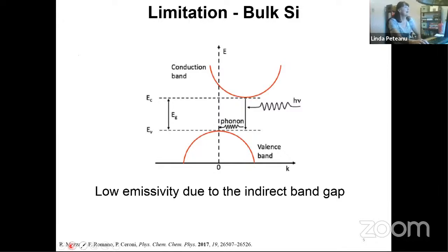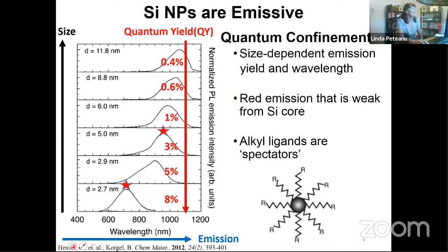So this crowd will know that bulk silicon is non-emissive because it's an indirect band gap material. However, as you make it into a nanoparticle type of system, you increase the emissivity up until about, let's say, 8% for very small particles. And this emissivity, the emission wavelength, is dependent on the core size, with the smallest size having emission around 700 nanometers. By about 5 nanometer particles, you get to about 700-800 nanometer emission, and beyond that, it effectively saturates. So the ligands that are on this surface here are essentially spectators and not really involved in the emissive process. The red emission that you see here is from the silicon core.